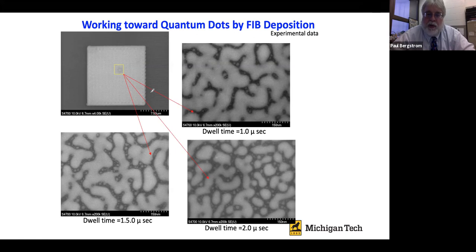In the process, as we were looking at the focused ion beam based deposition, we recognized that there's an amount of time required in order to fully decompose the source gas. But in that same time that the ion beam is depositing the film, the ion beam is still imparting kinetic energy to the substrate. So it also has an etching behavior. So what we came to recognize is that there is both a deposition and an etching happening at the same time in this process.